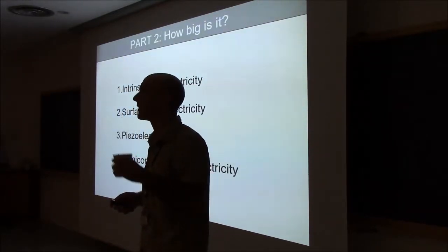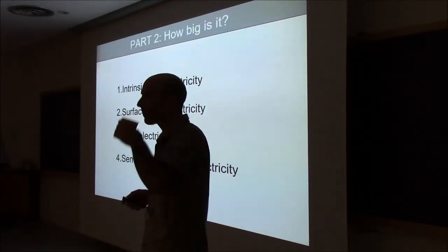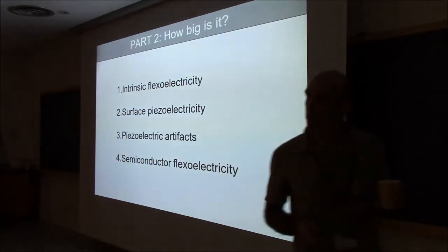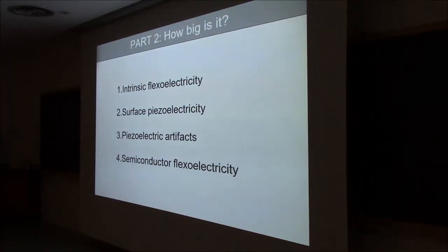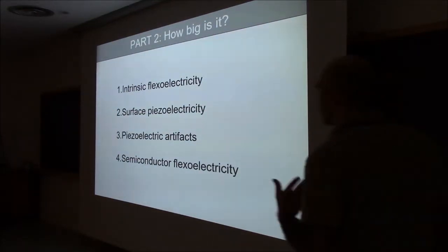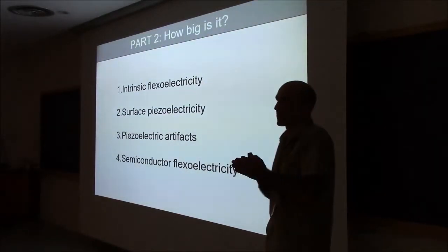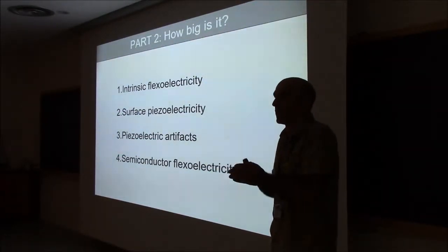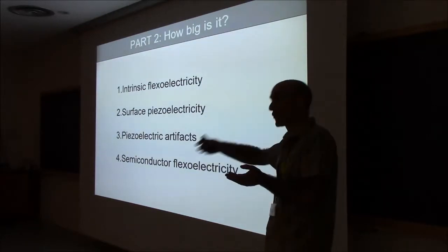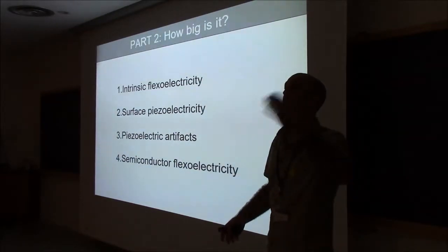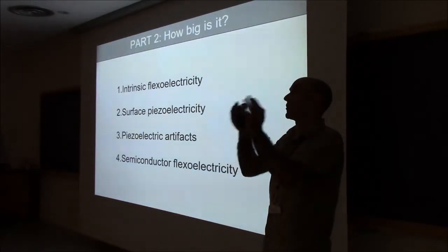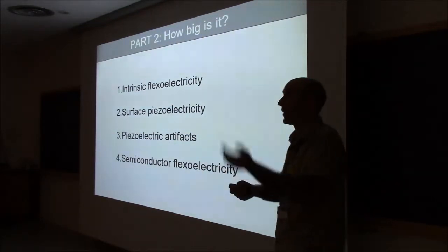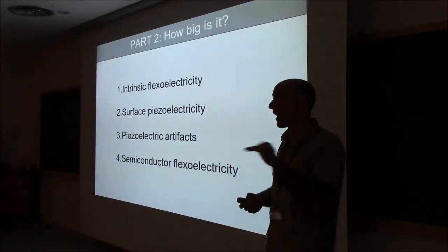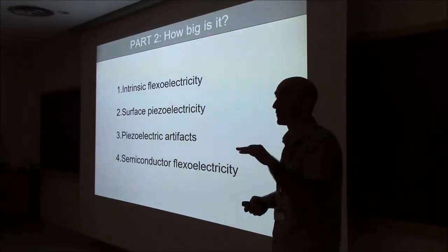In one of the slides, you showed that as temperature changes, there is change in the flexoelectricity. But when it goes up, does it follow the same points, or does it have any hysteresis also? Basically, as far as we can tell, flexoelectricity tracks exactly the dielectric constant. So whatever your dielectric constant does as a function of temperature is what your flexoelectricity will do as a function of temperature. Now, if you divide the flexoelectric coefficient by the dielectric constant, you get F, which is what he was asking, and F should be more or less temperature independent.